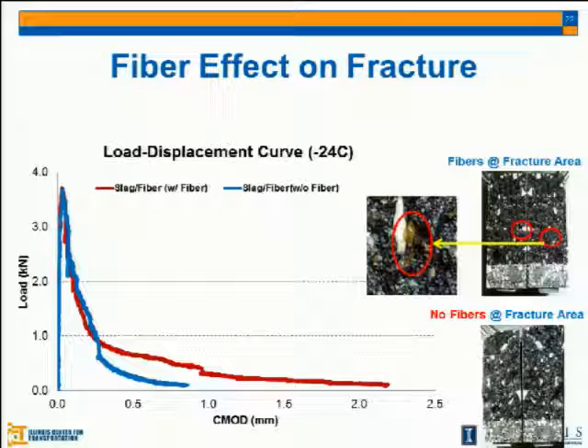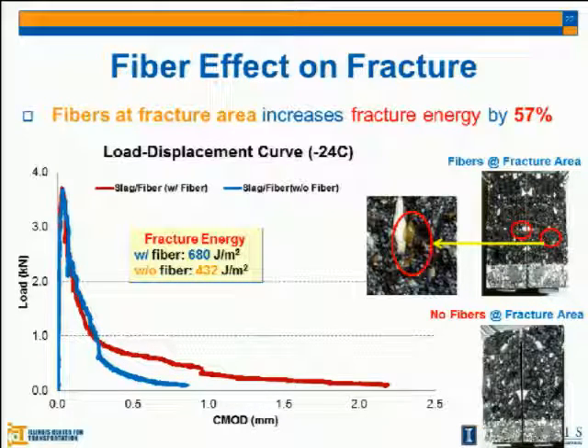So the blue one is without the fiber in this fractured face, but this red one had fiber in that area. So you can see the long tail of the fracture curve actually. That means the fiber holds the material after the crack initiates. So in this case, fiber at the fracture area increased the fracture energy by 57%.